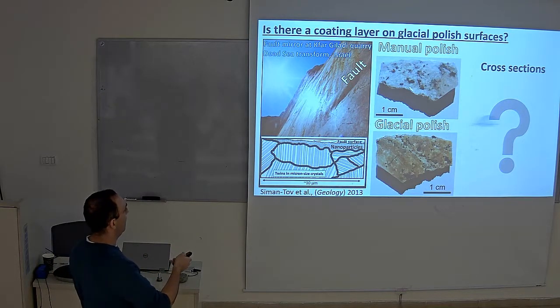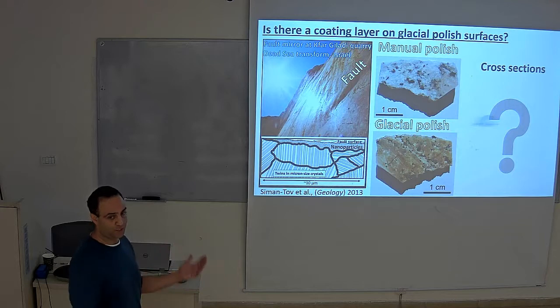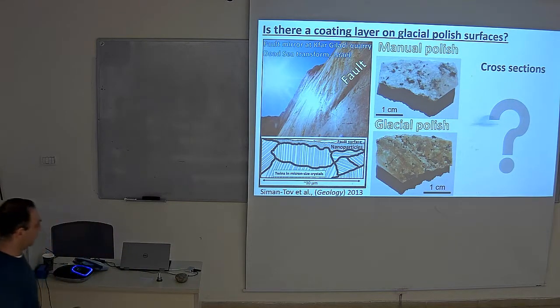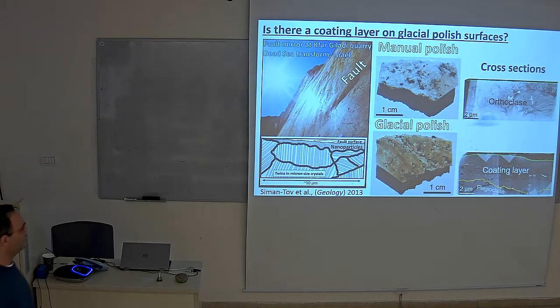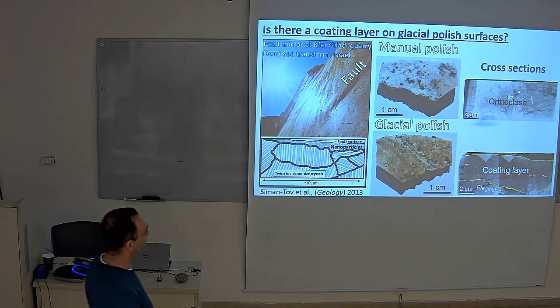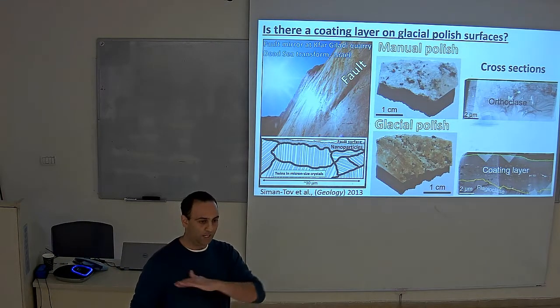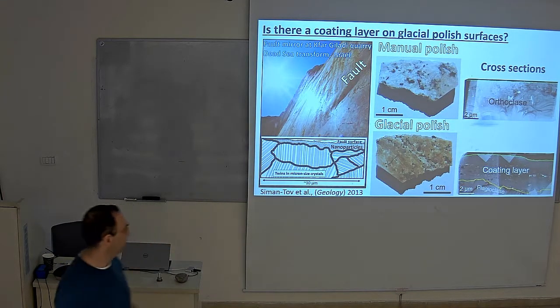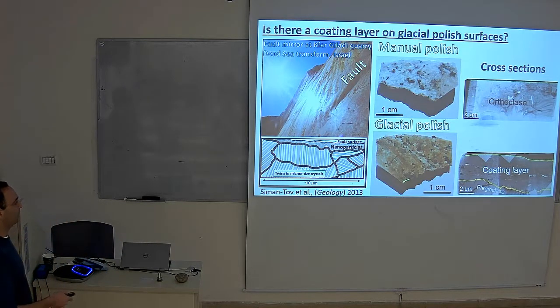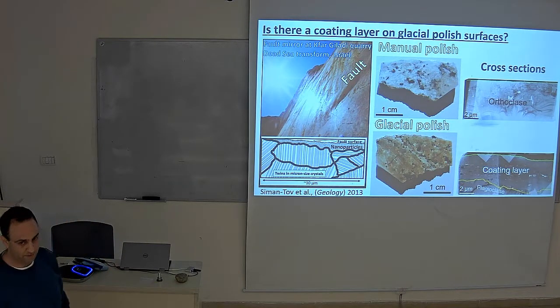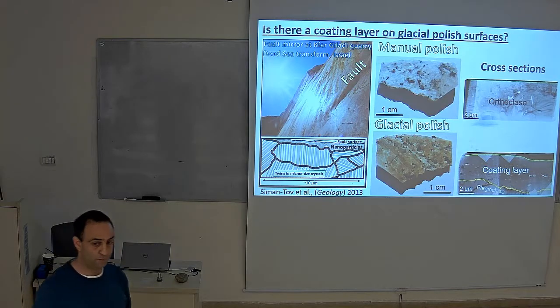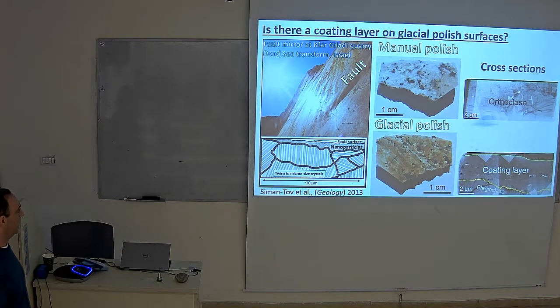And by the way, you can guess the answer already from this image. Here there is a different color for the glacial polish. Here it is more transparent, and we can see the original crystals. So the answer is yes, we can get a polish just by removal of material and having a very smooth topography. However, in glacial polish, we do observe a coating layer, a significant coating layer, between a micron to a few microns. So today I will concentrate on this coating layer, explain it, and what we can learn from it.